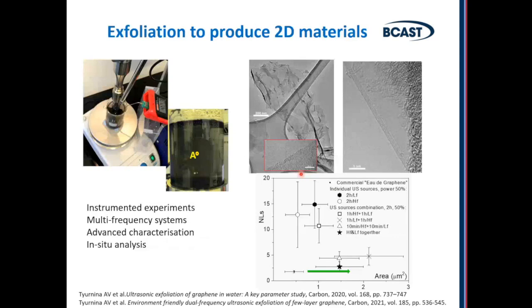In exfoliation, I mentioned graphene. So we developed a technology of making eco-friendly graphene purely by cavitation. If you don't know, currently graphene by liquid phase exfoliation is produced using chemical exfoliation. You add very poisonous and harsh chemicals to water or to other solutions, and these chemicals spread the crystal structure of graphite, kind of puffing it up, and then you use mechanical mixing or ultrasound to separate the layers of graphene. Here we don't use any chemicals, and the exfoliation happens naturally only by cavitation.